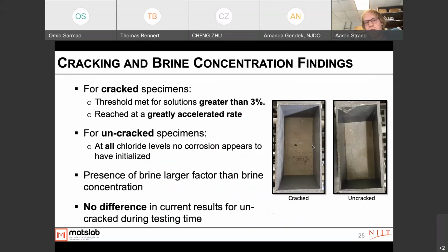So some of the findings from all of this are that for cracked specimens, if the ponding solution was above 3%, the threshold was reached at a greatly accelerated rate. And this is what we had figured. But what's interesting is that for all uncracked specimens, at all chloride levels, there was no corrosion that appeared to initiate, at least within the 1 year of testing. This was expected, as this is a diffusion mechanism, and that does occur over many years.